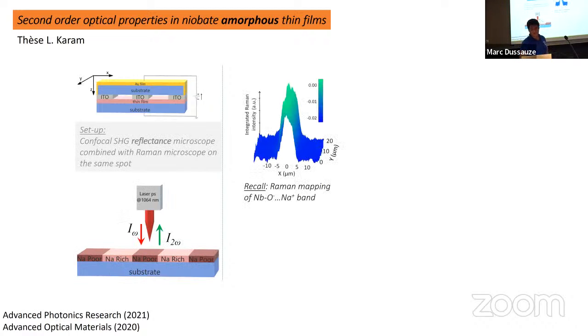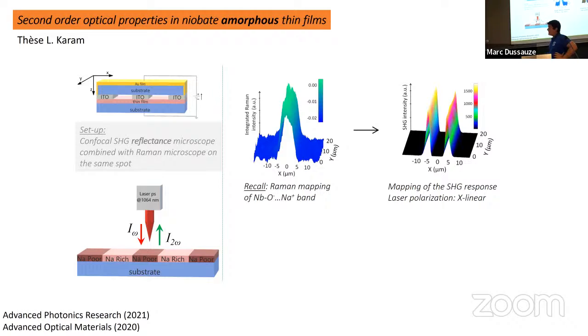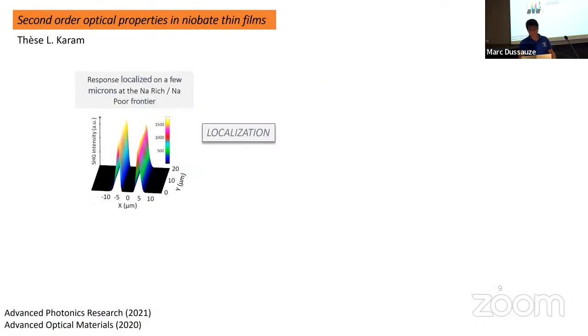So this is the map of the sodium repartition in the film. You see, you have one line of 10 microns thick, and the SHG response is located on each edge of the line. And you have a very strong response. Please look at these values. It goes from 0 to more than 3 orders of magnitude in a few microns. So it's very localized. It works very well. We can really imprint and locate the nonlinear response very accurately.